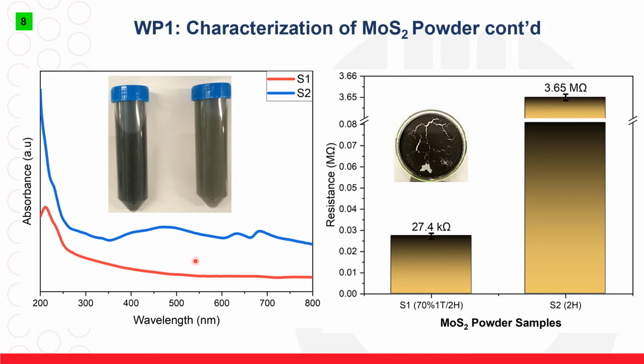The distinction of the molybdenum disulfide nanosheets prepared was clear with ultraviolet spectrophotometer characterization. The mixed phase molybdenum disulfide just had a smooth curve, whereas the single phase 2H molybdenum disulfide had two characteristic peaks at these locations, typical for the excitation in the Brillouin zone at the K point of the 2H phase. The suspensions were dark blue for the mixed phase molybdenum disulfide, whereas it was dark green for the 2H phase. And using an avometer, the electrical resistance of the two powders was also different.